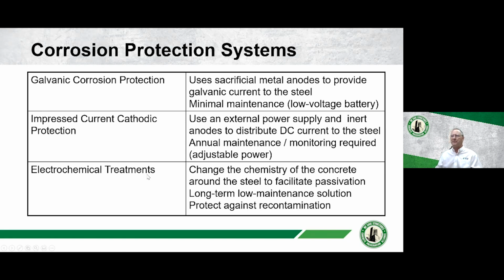And then we have electrochemical treatments, which is kind of like an impressed current cathodic protection system with a temporary anode that is run at a lot higher current density, which means it changes the chemistry of the concrete around the reinforcing steel. It kind of turns the clock back on the corrosion cell. And once it repassivates the steel, what you want to do is protect it against recontamination if you use electrochemical treatments. So those are the three types of corrosion protection systems.